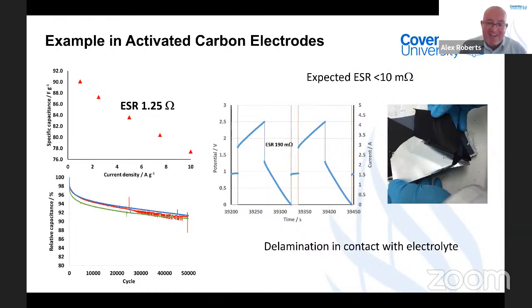So I still remember I went home, I cried a little bit. When I came back in the following day, I thought, right, it's time to cut these cells open and see what's happened. And it turns out I had a delamination problem. The electrodes seemed to have great adhesion, but as soon as I put them in contact with the electrolyte, they came off. And you can see that happening in the picture in the inset.